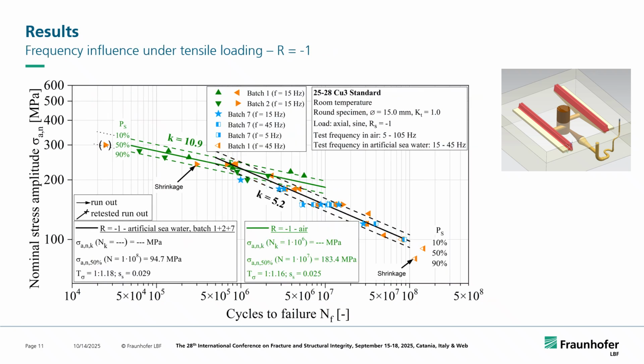We wanted to see the frequency influence as well, and so we went on with those tests on the alternating loading. What you see here is some specimens from a batch 7, also taken from another casting, from those first main design that we use from those 50 millimeter bars, so directly comparable from the microstructure and from the casting process. And then we made some tests, and what we see here in blue are specimens under 15, 45, and 5 Hertz. They match really well, first of all, with batch 1 and 2. That's what I showed you on the slide before. And the most important thing here is that both 5 Hertz and 45 Hertz test results match within the scatter band of our initial SN curve under 15 Hertz.